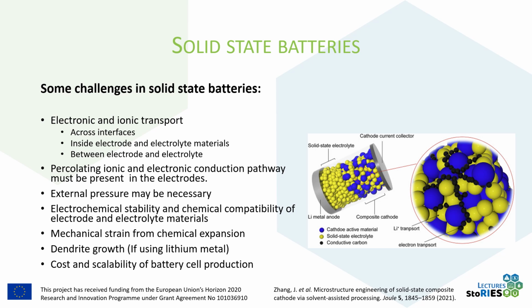Also, transport of ions inside a solid is much more difficult than in a liquid, requiring development of solid electrolytes with high ionic conductivity. The ions have to travel between the electrode and the electrolyte, and the boundary resistance and the contact area have to be optimized. In the electrode, we need percolating ionic and electronic conduction pathways. This means that ions and electrons should easily be transported to the solid electrolyte and the current collector, respectively. The cathode is therefore a composite between an active material, a solid electrolyte, and a conducting phase, for instance carbon black.